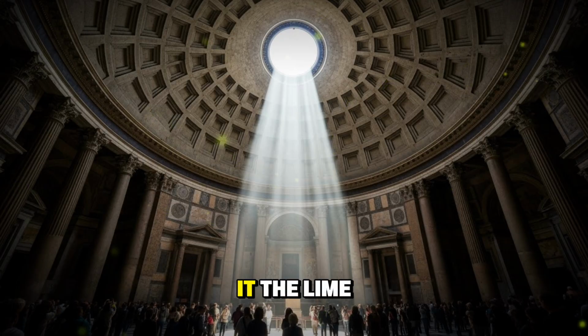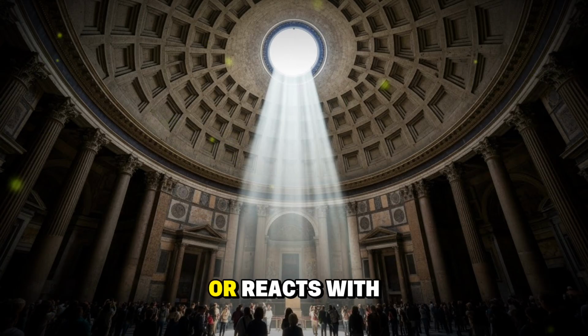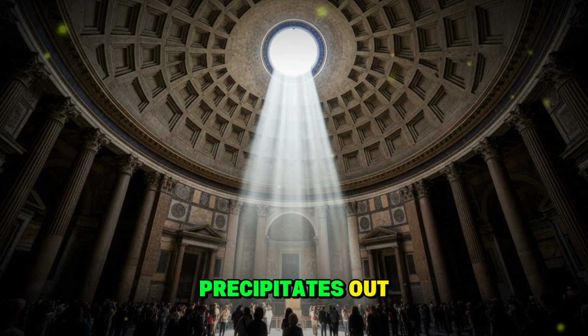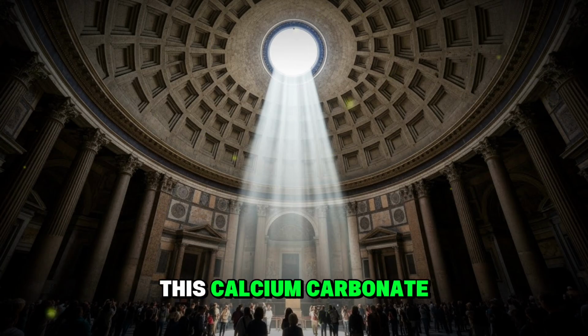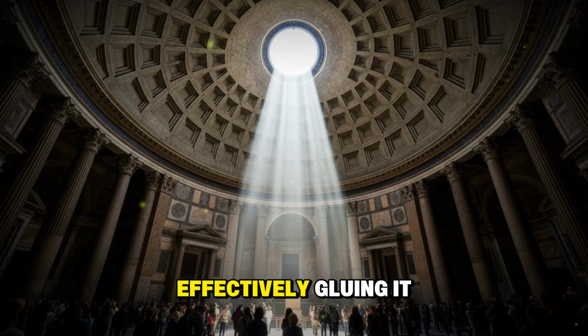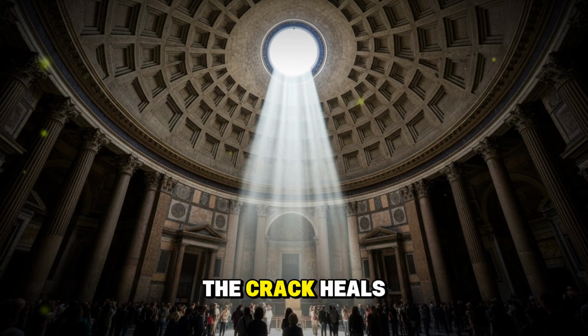When water touches it, the lime dissolves into the water, creating a calcium-rich solution. This solution flows into the crack, filling it. Then, as the water evaporates or reacts with carbon dioxide in the air, the dissolved calcium precipitates out. It crystallizes as calcium carbonate, the same material as limestone. This calcium carbonate bonds to the edges of the crack, effectively gluing it back together. The crack heals itself. The concrete doesn't just survive, it repairs its own damage.